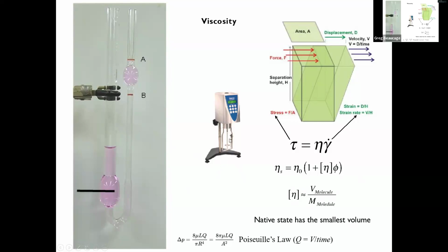This is showing another kind of viscometer, a cup and bob viscometer, so it'd be a cup around this, and that's the bob or the spindle, which can be of different shapes. So that one's a cylinder, and that one is just a rod that goes into that fluid. This is also the kind of viscometer they use for paint and stuff industrially, except without the cup. So you just stick something into the paint and spin it and see what the torque is on it. So people use that. This is kind of better in a sense because you get a more controlled flow field.